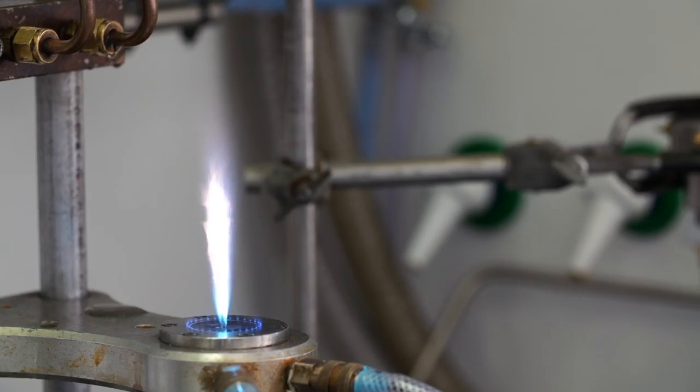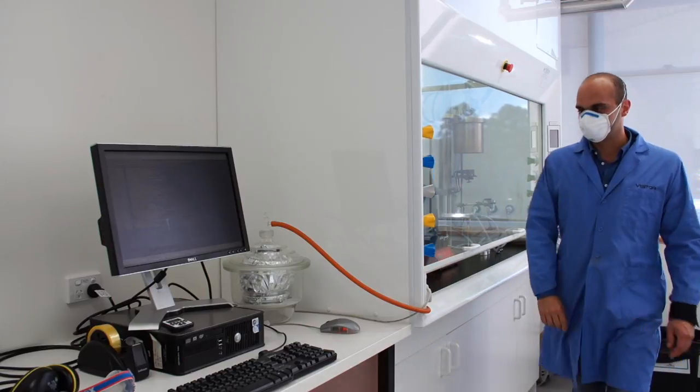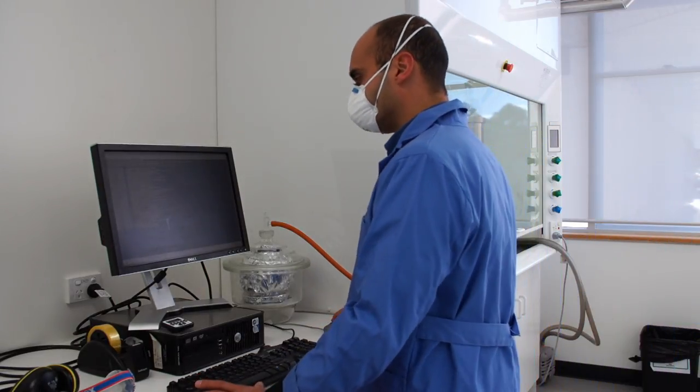What we can do is use a flame spray technique, which is lower temperature and results in a sponge-like formation of this synthetic bone, which really mimics the bone environment within our bodies. This is low cost, scalable, and we can assemble these coatings on the implants within 15 seconds.